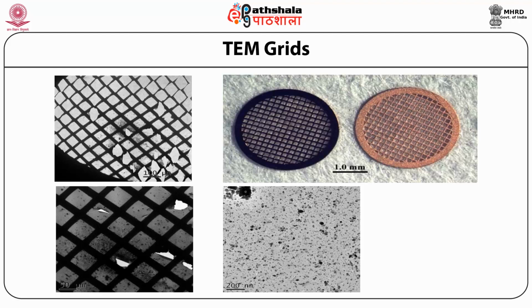In the next image one can see that there is a sample lying down, and this can be imaged inside the microscope, where you have grids, and on top of that there is a formvar film and very small black spot samples. If you zoom in more and more, then you will end up getting nanoparticles, which is shown in this figure at the end, where a small nanoparticle with a resolution of 20 nanometer has been shown, where one can see that the very tiny nanoparticles are resolved, which is the beauty of the transmission electron microscope.